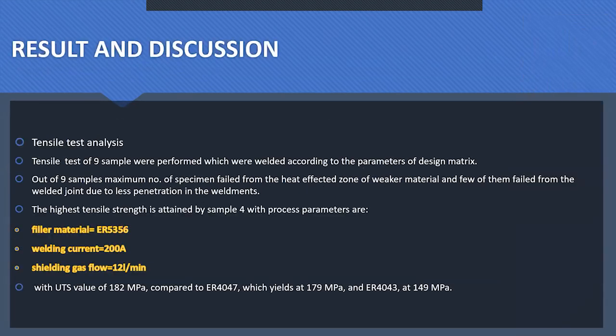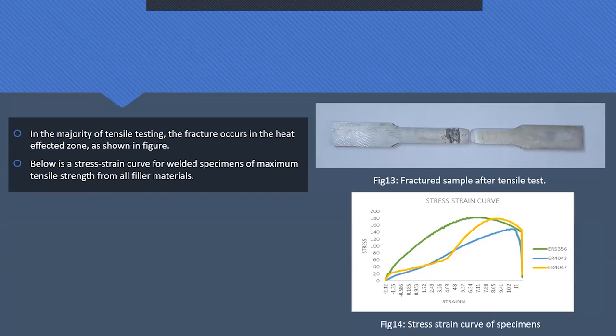Now coming to results and discussion. A total of 9 specimens have been tested. In tensile testing, the highest UTS value achieved is 182 megapascal, in the specimen with filler material 5356, welding current 200 ampere, and shielding gas flow 12 liters per minute. In other filler materials, in the case of 4047, the highest UTS value we achieve is 179 megapascal, and in the case of 4043, the value is 149 megapascal. These are the tested specimens. The fracture has been found in the heat affected zone of the weaker material. The majority of specimens failed for this reason, and a few of them failed in the weld due to less penetration. These are the stress strain curves of 3 different specimens comprising 3 different filler materials. The optimum specimen has been used for the preparation of the stress strain curve.